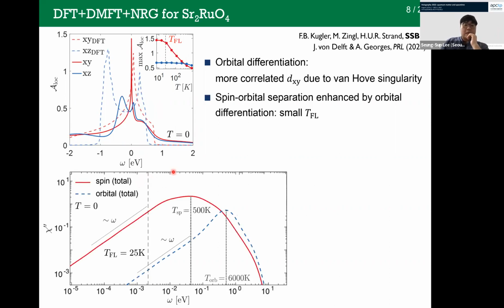And what we also studied is the spin orbital separation. This is a similar type of plot I showed earlier. So these are the susceptibilities, the imaginary part of spin-spin correlation or orbital-orbital correlation on the log-log axis. We see that the spin screening energy scale is much smaller than the orbital screening energy scale. And we found that this orbital differentiation further pushed the spin orbital separation. If there were no orbital differentiation, the separation would be less than what we see by now.